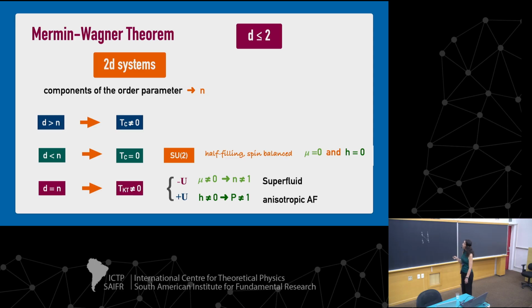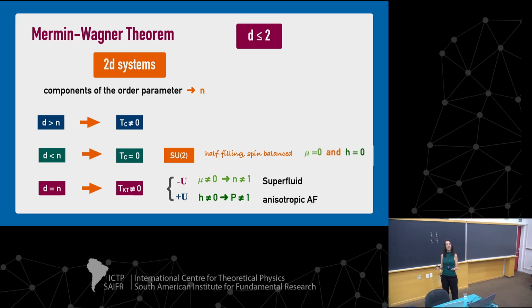And coming back to the Mermin-Wagner theorem, this is a theorem that applies to systems with dimension smaller than or equal to 2. Here we are discussing this in 2D. And what it says is related to the number of components of the order parameter. So if the dimension is larger than the number of components of the order parameter, then you can have TC different than 0. This is what happens when we have an Ising-like model, where spins can either point up or down. Then the number n of components of the order parameter is 1, and you can have TC different than 0 at 2D.